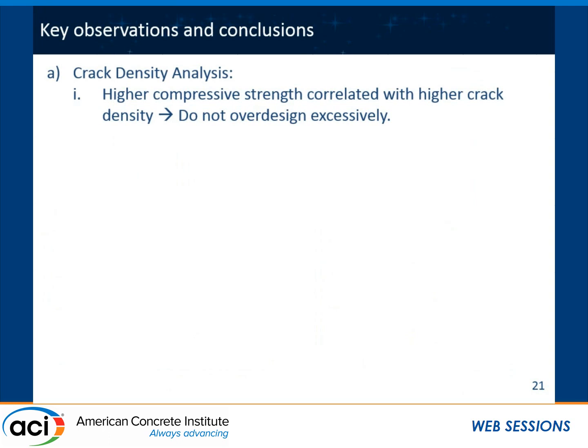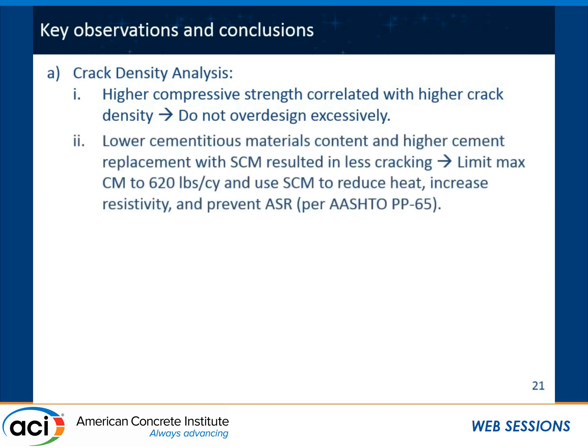From the crack density analysis, we learned that a higher compressive strength correlated with a higher crack density. And really the take-home message is do not over-design excessively. So if we need 4,000 PSI, probably we want to make sure that concrete is not above 5,000 PSI. Over-design is not helping us.